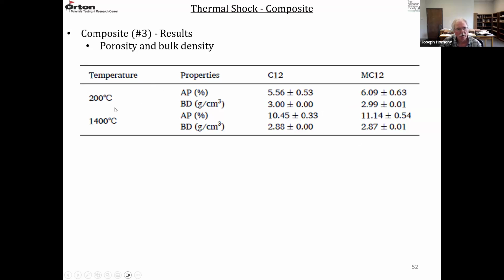So when you cure this from 200 to 1400, you pyrolyze the phenolic resin. You have, let's say, a 50% carbon yield, then you have a 50% loss on ignition of that resin. So the porosity goes up, from about 5 to 10, 6 to 11, and then the density drops from about 3 to 2.88 and about 3 to 2.87. So the pyrolysis step or the coking step increases the porosity and decreases the density.